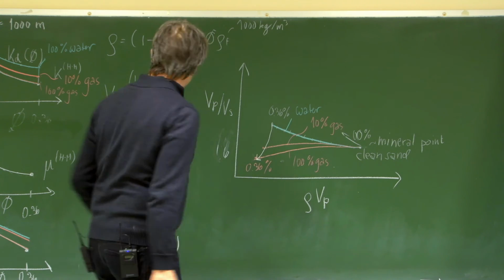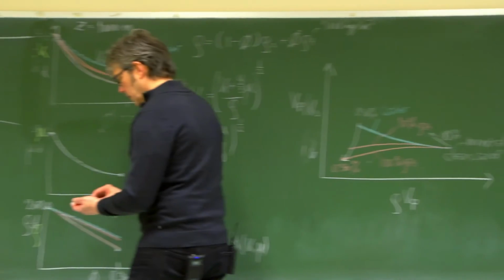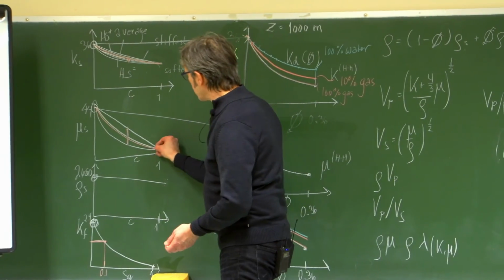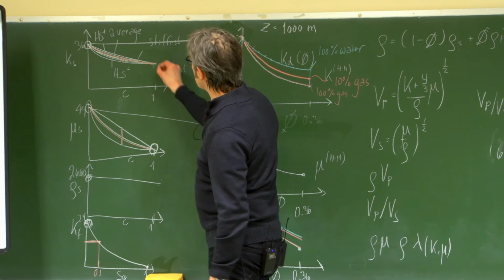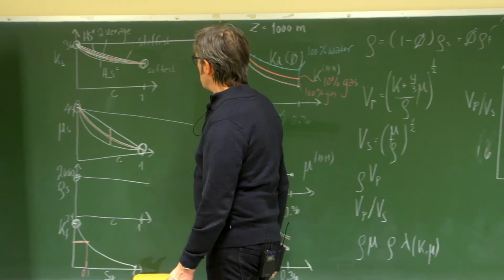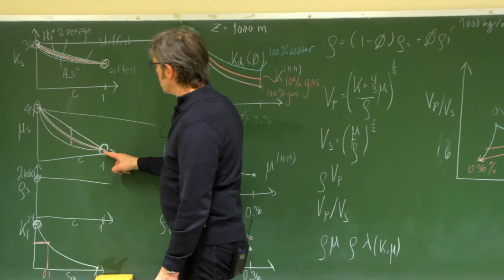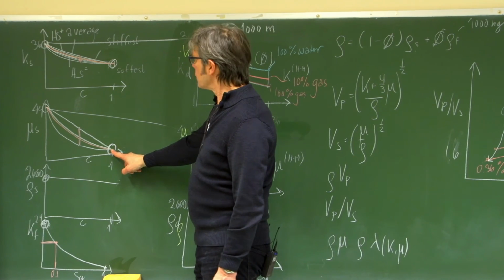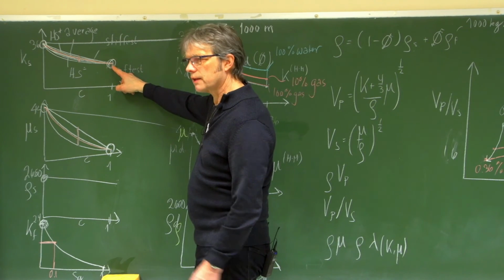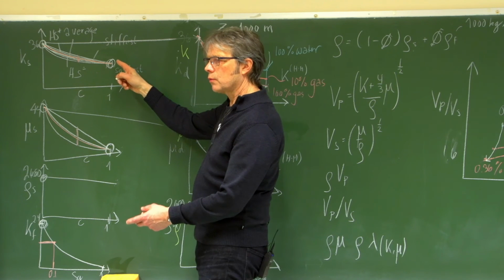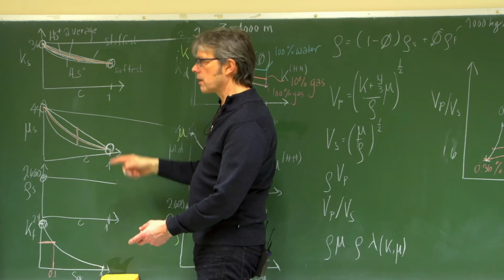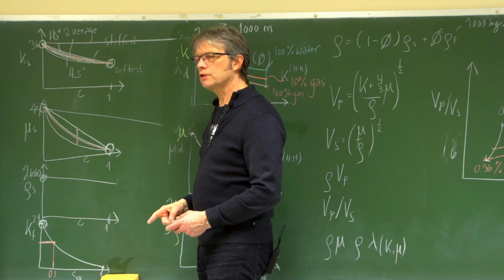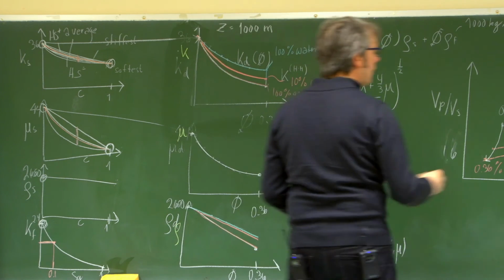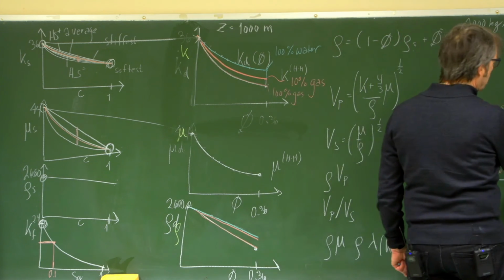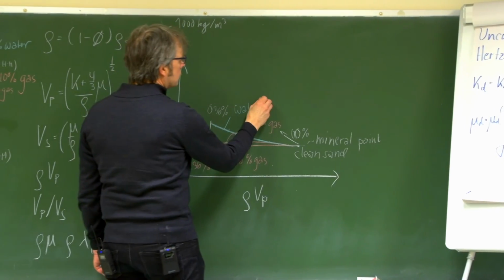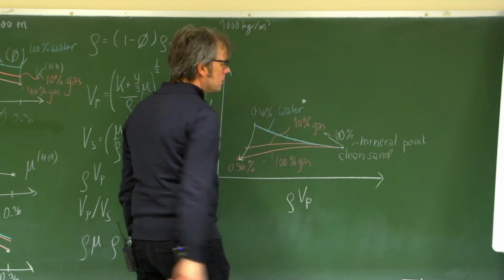So if I did the same just with the pure clay over here and here, I use 7 for the shear modulus, 21 for the bulk modulus, and then you see that, okay, with a very high bulk compared to a shear, I would have a high VP/VS ratio for the mineral point. And that's exactly what happens. The mineral point would increase quite a lot.